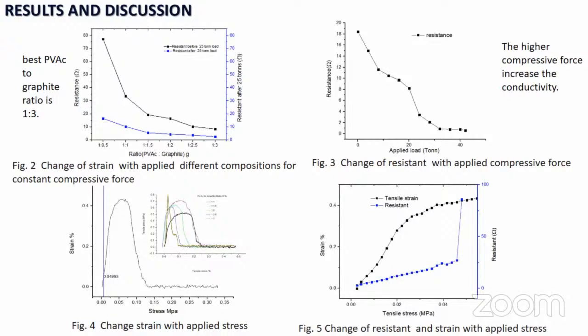This may happen due to the compression of the materials inside the composite. In figure 3, you can see the resistance change with the applied load. When we apply the load, the graphite structure will come close and the resistance will gradually lower. In figure 5, we can see the resistance change with stress in megapascal values and also the strain. After a small amount of strain, the structure will lose the conductivity, and after some time the structure will fail.